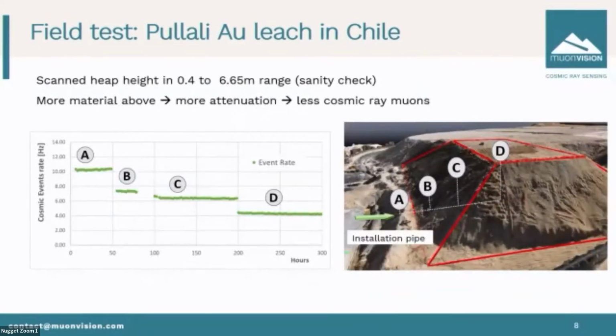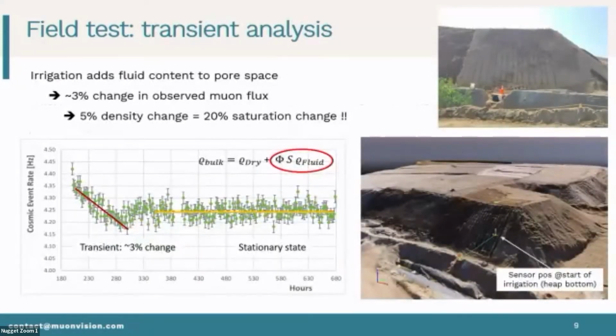All right, so we did some initial sanity checks. As the material was being deposited, we started moving the sensor to different locations. These different locations have different amounts of material above, and as you would expect, you would detect fewer cosmic ray muons. We start from about 10 per second and we drop all the way. Then we reached the final location, which was actually the moment when the operator started the irrigation.